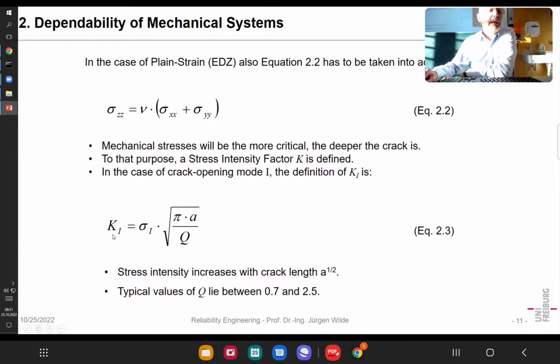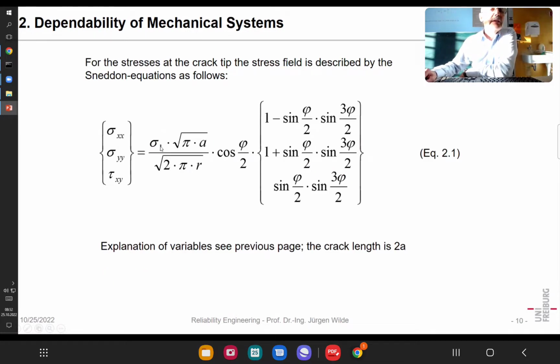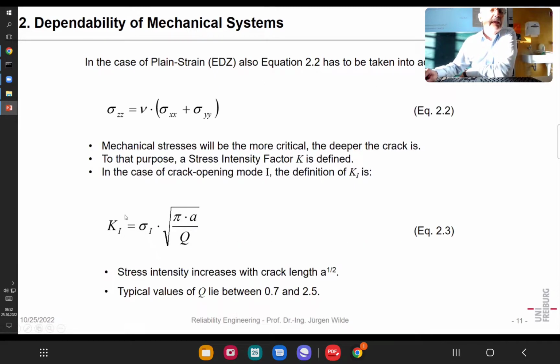Generally, you can say that stress concentration, as you see it here, and having these geometry factors, can be described for all, let's say, representative cases. That's nominal stress multiplied with pi times the crack length, so that's the length from the surface of the part to the tip of the crack. And Q is a geometry factor depending on the special case. Let's say for us here, we say Q is by definition 1, but it can be between 0.7 and 2.5.